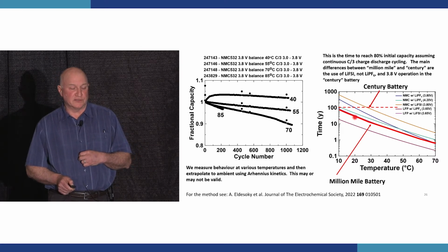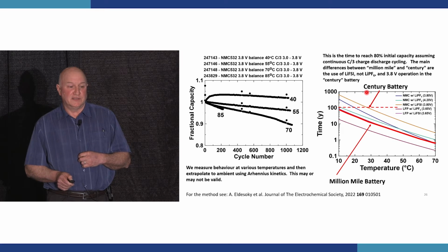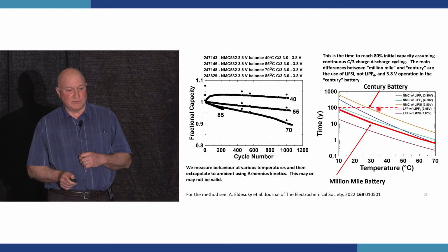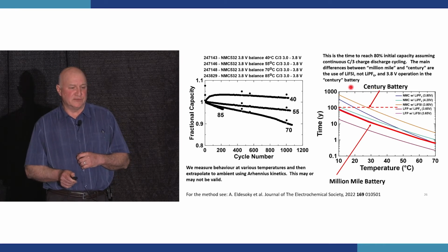that we made earlier. And then this battery that we've been talking about now with NMC 532 and LiFSI electrolyte salt, balanced and operated at 3.8 volts, this is the lifetime versus operating temperature plot. And at a temperature of 27 degrees C, it would last 100 years. So you could call this thing the century battery if you like.